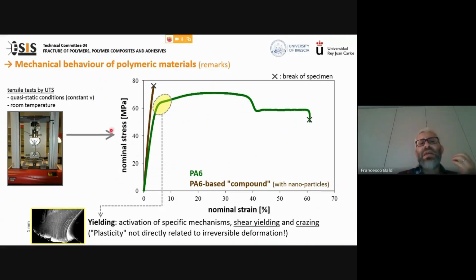If I switch to the mechanical behavior of polymeric materials, the first thing that we have to say is that the mechanical response of a polymeric material can change remarkably from polymer to polymer. And just to give an idea, I have reported this graph in which there are two stress strain curves obtained from tensile test on a PA6, the green curve, and on a compound that is based on that PA6, and this is its stress strain curve represented here as a brown curve.